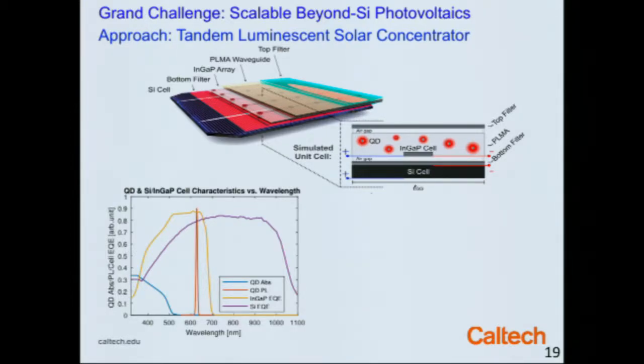So the scheme here is light comes in, is trapped inside this waveguide, trapped by the mirrors, absorbed by the quantum dots, re-emitted as luminescence radiation - very similar to the process I described in gallium arsenide, but now inside a polymer waveguide - and then is absorbed by the indium gallium phosphide solar cells.